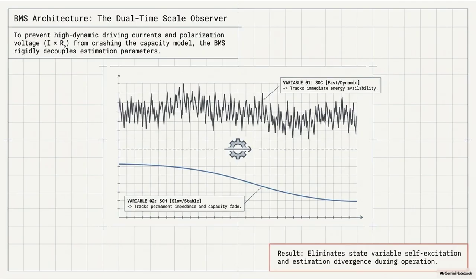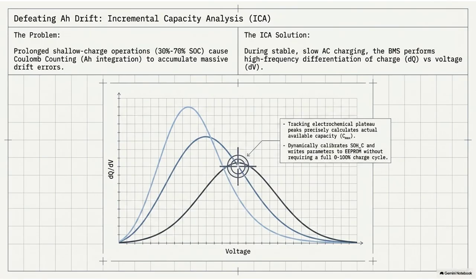But EV owners rarely do full 0 to 100% deep cycles. Exactly. They commute, they plug in at 40%, they unplug at 80%. These constant shallow microcycles cause that tiny sensor offset error to compound mathematically over months. The turnstile loses count. The BMS might calculate the pack has, say, 65 kilowatt hours of usable capacity based on integrated current, but due to drift and the physical LLI decay, the true physical capacity might only be 58 kilowatt hours. And to correct this, without forcing the driver to purposely drain their battery to zero on the side of the road, the BMS deploys a brilliant diagnostic algorithm.